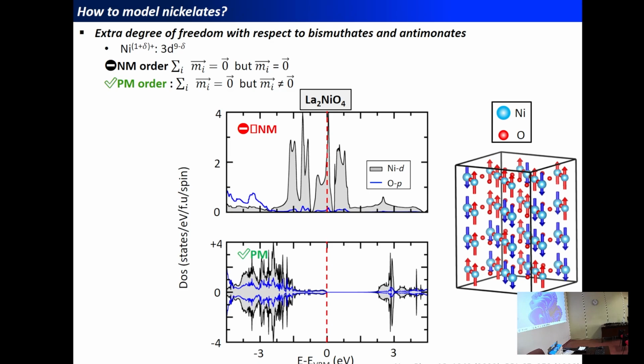And if we do that, you see that for the starting member, the n equals 1 member, we end up with a metallic system. While if we use a paramagnetic representation of the spin with a random orientation for the spin, still at the collinear level, where we just restrict to spin up and spin down, it's sufficient to have a collection of what we can have in a real paramagnet. So we ensure that the sum of the magnetic moment is exactly 0, but then we allow each transition metal site to develop a magnetic moment. And if we do that, effectively, we end up with a Mott insulating character for the starting member.